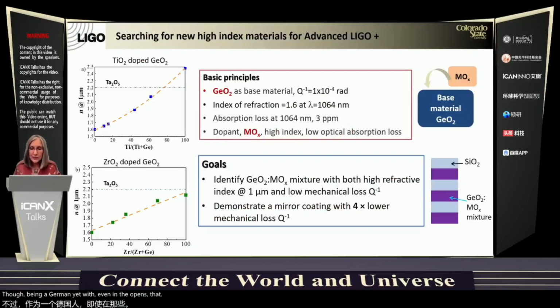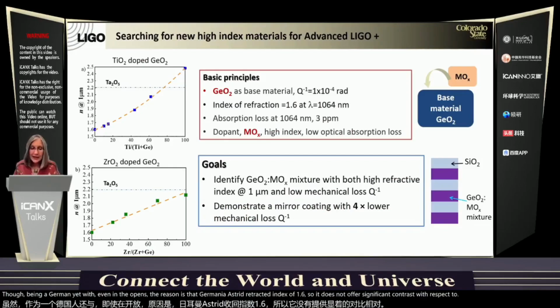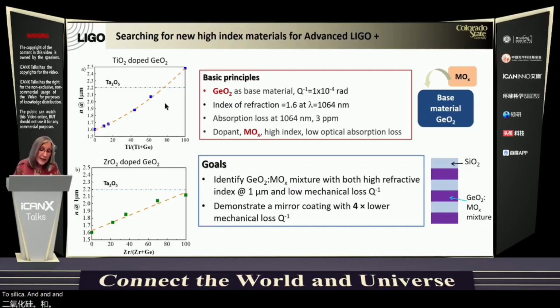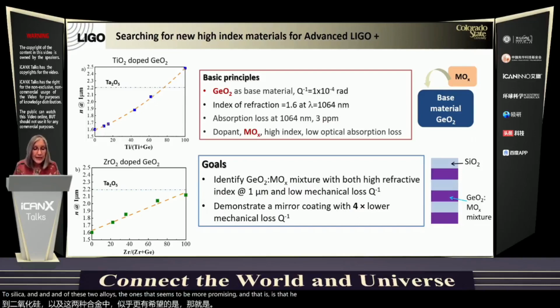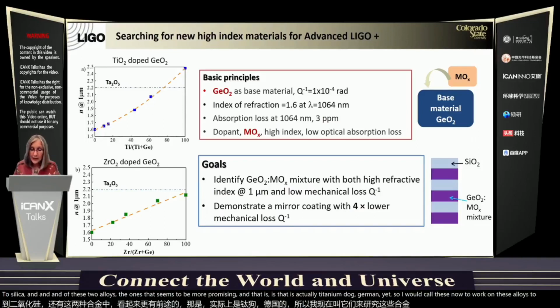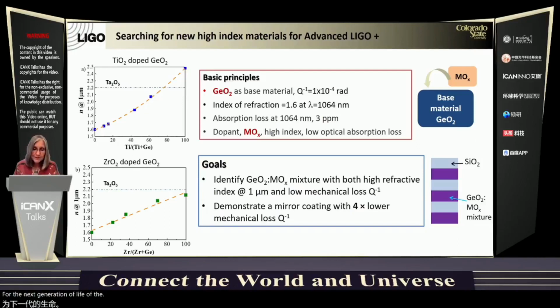The reason is that Germania has a refractive index of 1.6, so it does not offer significant contrast with respect to silica. And of these 2 alloys, the one that seems to be more promising is titania-doped Germania. So our goal is now to work on this alloy to obtain an alloy that will have 4x lower mechanical loss for the next generation of LIGO coatings.